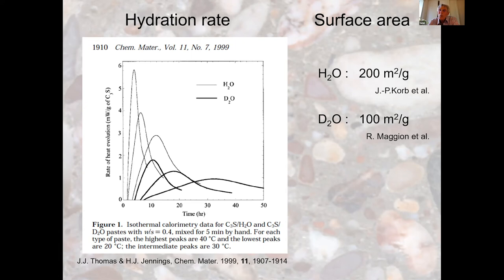What is also very strange is that the surface area accessible to water or to heavy water is very different, as you measure by NMR, which is now a classical method. A paste hydrated with light water has a measured surface area by NMR of 200 square meters per gram. If you perform hydration with D2O, it's only half of it. Well, I think understanding this is still an open problem, but it points to something which is pretty clear, I think, that there is a special link between water and the hydrates in the case of cement pastes.